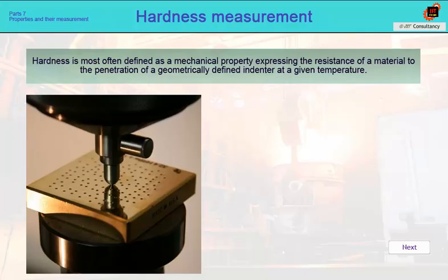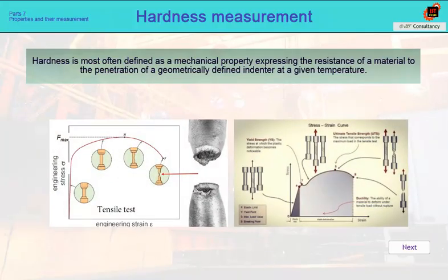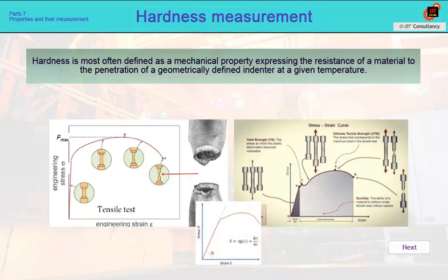It depends on many material properties, but primarily on the elastic properties, the modulus of elasticity E of the tested material, and on its plasticity. In terms of hardness values, each material therefore behaves differently. However, since the design of various assemblies often also depends on the difference in hardness, it is a constant effort to compare these values and therefore to measure them.